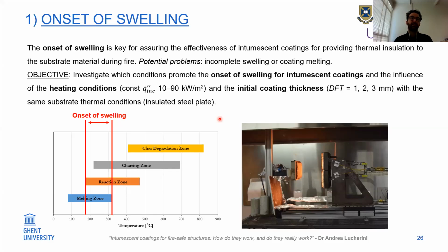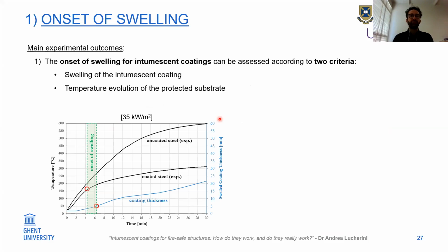The substrate thermal conditions were always the same: a steel plate, 10 millimeter thick, insulated at the back. The first result you can see here is, for example, for 35 kilowatt per square meter. On the left axis you can see the temperature. This is the temperature that an uncoated steel plate exposed to 35 kilowatt per square meter would follow, and this is the temperature of a coated steel plate. You can see that at a certain point there is a sort of bifurcation between these curves, because the coating starts the swelling process.